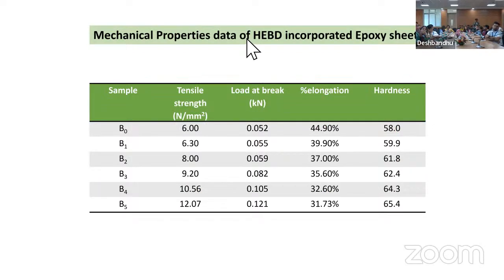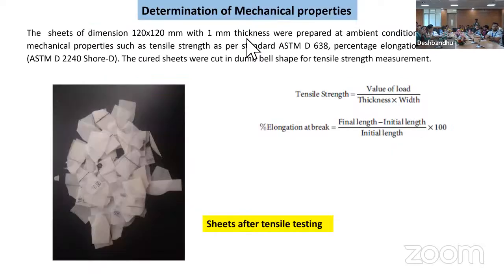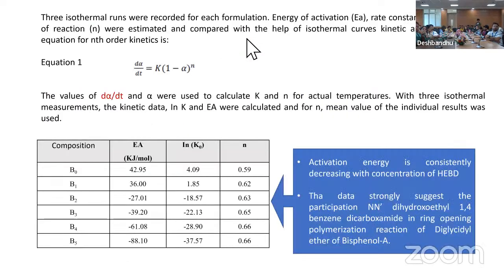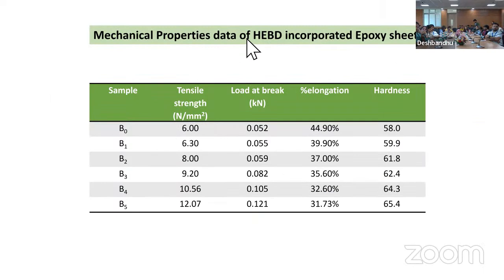Importantly, tensile strength is increasing from 6 Newton per mm square to 12.07. And there's a decrease in percentage elongation. So we are not compromising that much on the percentage elongation, but tensile strength is increasing. It has just become double from B0 to B5. Hardness is also increasing.